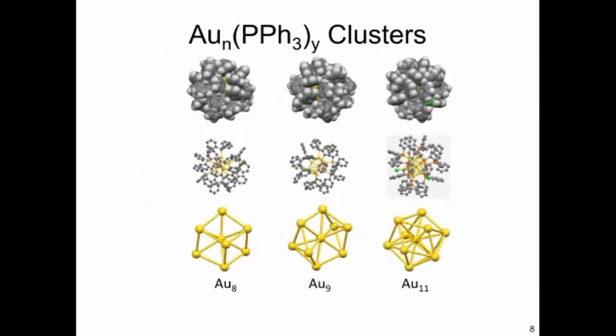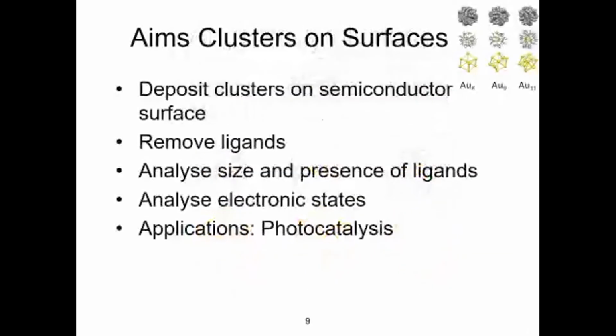The group we work with, as chemists, are producing gold 8, 9 and 11 exactly. They measure and screen it by NMR and also different mass spectrometers. The purification is a bit difficult for this nanocluster to have it in precise atoms. We deposit them and we remove the ligands, because at the end we need access to the gold core of the cluster itself, and we use it for the application.